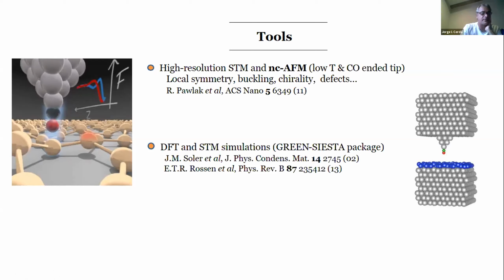we've been doing a lot of simulations at the same time, basically DFT-based simulations. First, for total energies, this will tell us which phases are more stable on the surface. We've also done STM simulations. In the STM simulations, we've taken care of the actual tip structure. We use the non-equilibrium Green's function formalism and explicitly simulate the tip with whatever we want to functionalize it with. Here would be the substrate with the silicene on top. And then we actually explicitly calculate the current, so we can generate topographic maps very similar to what is generated experimentally.